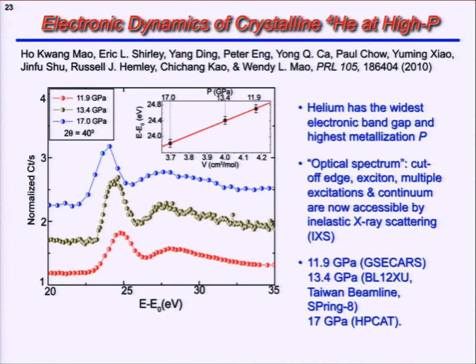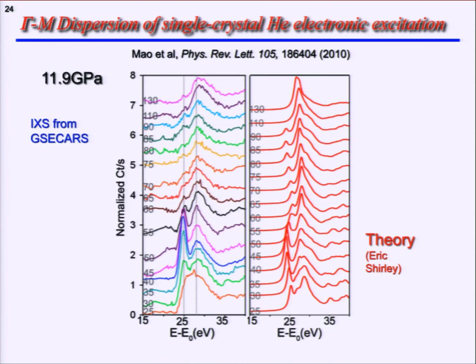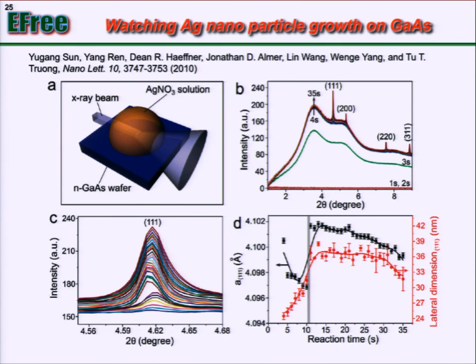Helium also has many excitons in this region. The exciton here is a low energy exciton, and has also been widely used for energy application. In fact, there are 2 centers out of 46 centers dealing with excitons. One of them is just called the excitonic center. But with X-ray, related to the development of X-ray techniques, we can use inelastic scattering. This is equivalent to the energy loss technique of electron microscopy. We can study not only the helium band edge gap but also the exciton dispersion as a function of momentum, and so we can get the whole picture of the excitonic structure of helium.